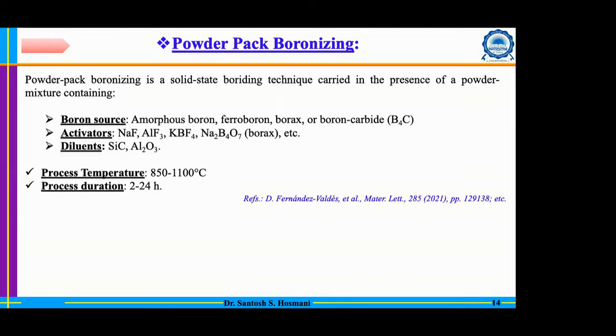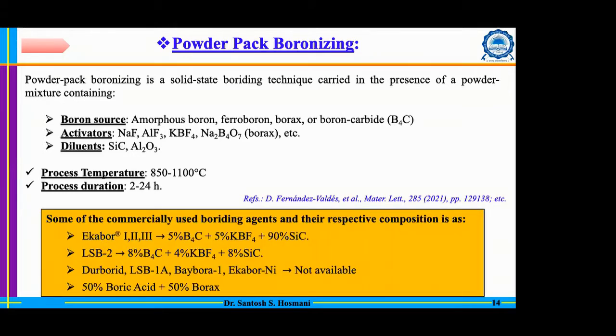Then the process temperature, as I mentioned, in principle you can go even as low as 800 or 850 degrees Celsius and as high as 1100 degrees Celsius. The duration will vary depending on the thickness you are looking for, and people generally use a range from 2 to 24 hours. Of course, 24 hours is too large a duration, and many times it's not required. Even 6 hours or even 4 hours is good enough to get a layer thickness in microns. So that advantage is there, especially in the boronizing process. Now the commercial suppliers. There are various commercial suppliers, for example Ekabor, a German supplier, which supplies these boronizing powders.